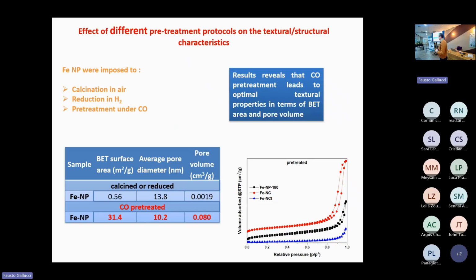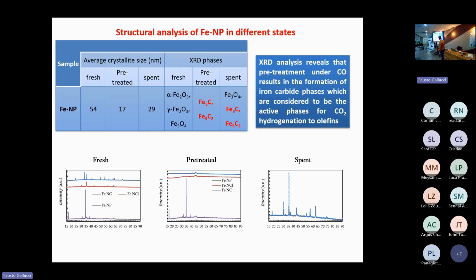And the results clearly reveal that CO pretreatment results in the best textural properties in terms of BET surface area and pore volume. Notably, XRD analysis reveals the formation of iron carbide phases only under CO pretreatment. Later, the hydrogen activation or calcination will result in the highly active carbide phases.